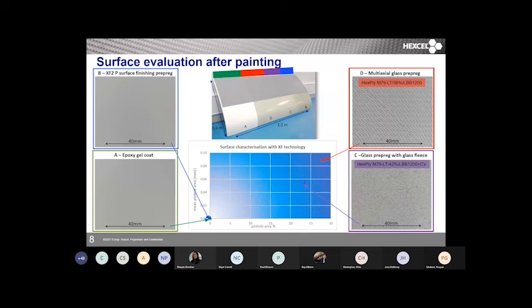and that's going to take a lot of time to get a good surface finish. Now, the baseline, the performance that you have to match, is gel coat. That's the incumbent technology, and you can see that's basically 0-0 on our chart, highlighted with green. Now, XF technology sits almost on top of it. There are a few pinholes, and they are tiny. They're of the size that if you've got good equipment and you go looking for them, you can quantify them. But we have experience with several hundred blades being manufactured with this technology, and they don't impact the painting process. They're below the threshold value where they become a problem.